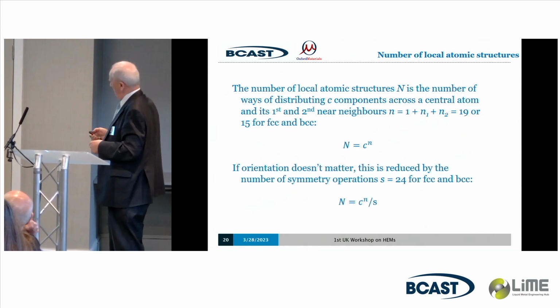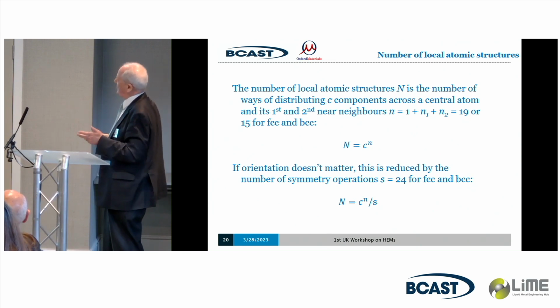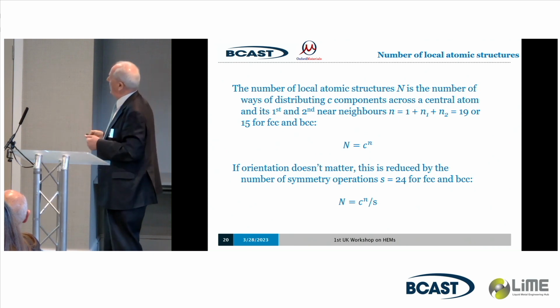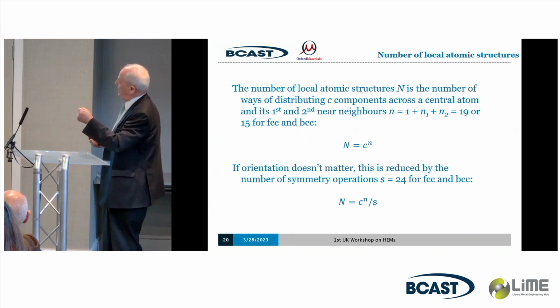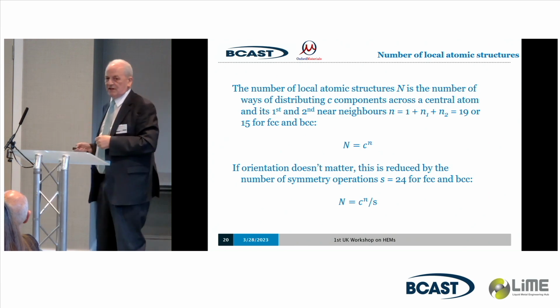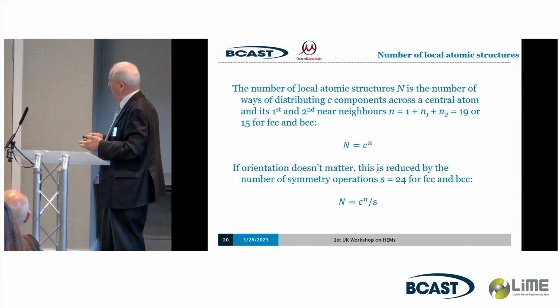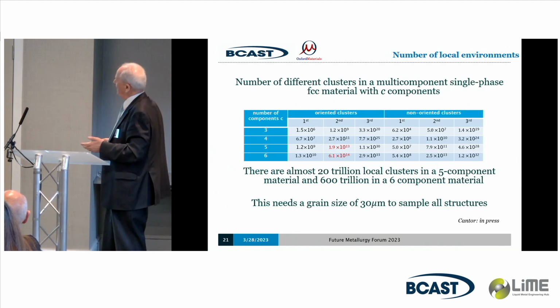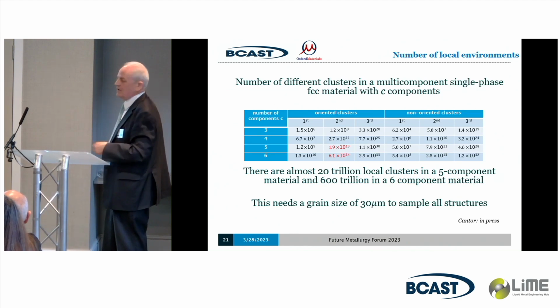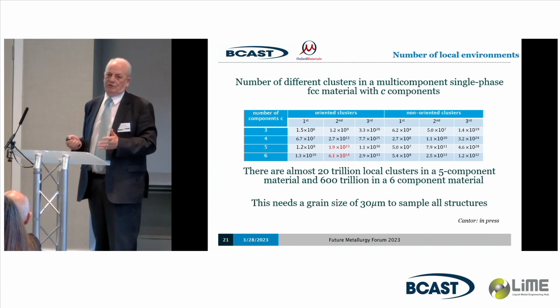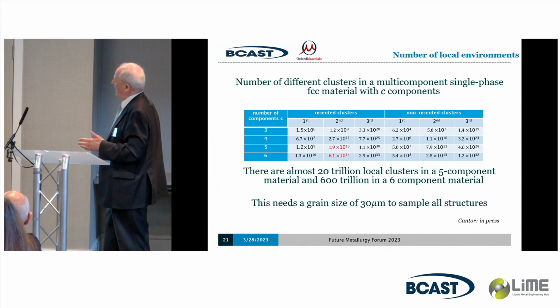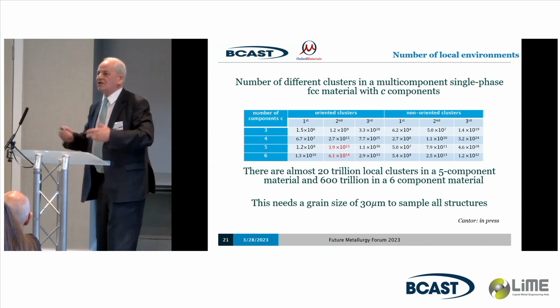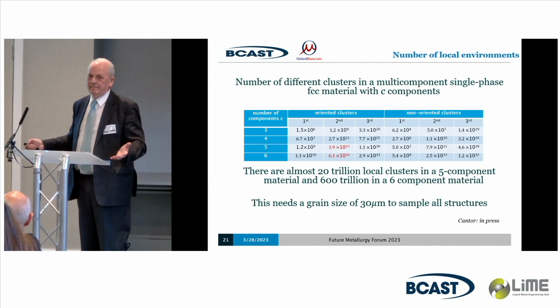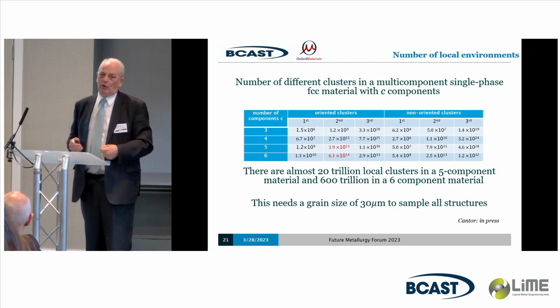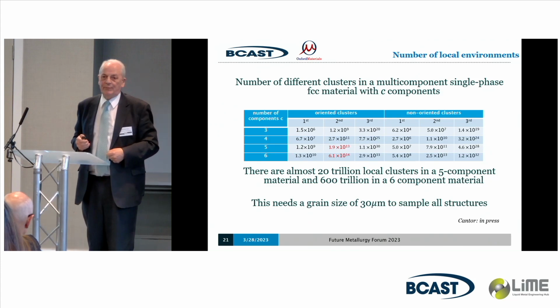So we ask ourselves, how many local structures are there? Well, the number of local atomic structures is the number of ways of distributing C components, in a 5-component system that would be 5, across a central atom and its first and second near neighbours, which is 19 atoms for FCC. The answer is C to the n, which if you calculate it for the Cantor alloy 5-component system is 20 trillion. There are 20 trillion different local structures. To put it crudely, you need a grain size of 30 micron to sample all of the different structures there are. So, put it another way, if you have grain sizes smaller than 30 microns, each grain could have a different property.